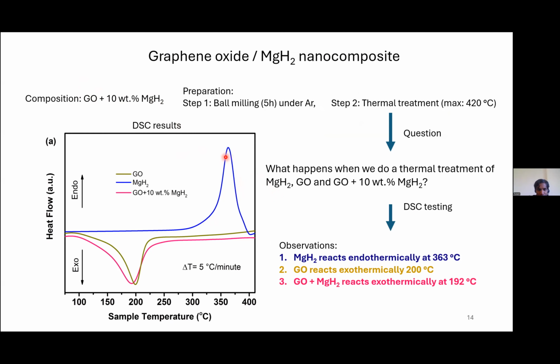Magnesium hydride, the blue profile, okay? Ball milled magnesium hydride endothermically releases hydrogen at almost around 350. Fine. And what about graphene oxide? That reacts at around 200 degrees centigrade. The reaction is exothermic. So when you mix graphene oxide and magnesium hydride, if there is absolutely no reaction, you would expect two steps, one exothermic and one endothermic step, and no changes in the dehydrogenation or the transfer phenomena. But what we are observing is a one-step reaction at a slightly lower temperature. That means there is an interesting chemical reaction between them. What chemical reaction is that? And that we are interested in.